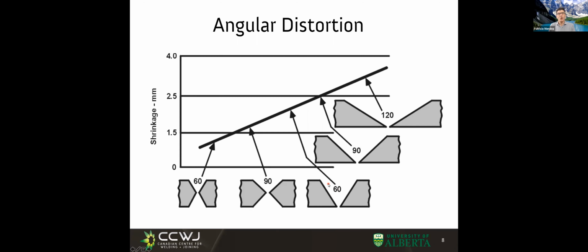Now, let's compare with the opening of the V. And guess what? Something that was not too difficult to imagine. As the V is more and more open, the angular distortion is higher and higher. This vertical axis is measured in millimeters for a particular case, as they measure the distortion and see how much one of the sides lifted. I'm not worried about these exact numbers, just the trends. And the trend is that big open V's have a lot more distortion than narrower V's, and I could reduce it even more by having a double V joint preparation.